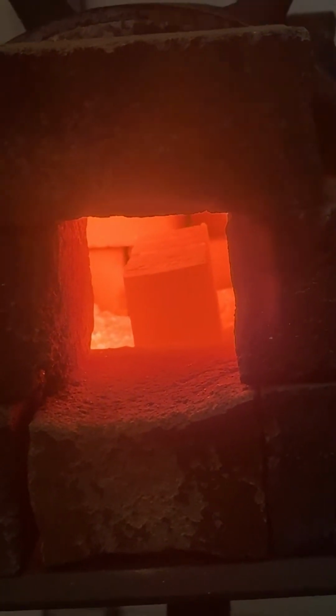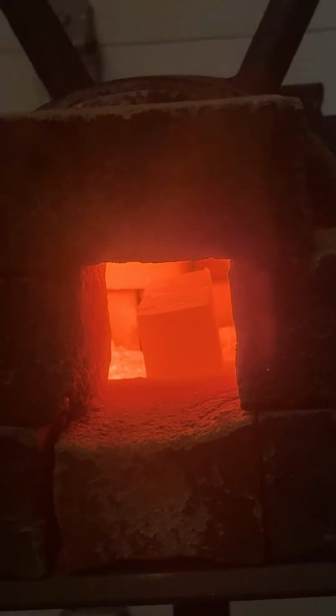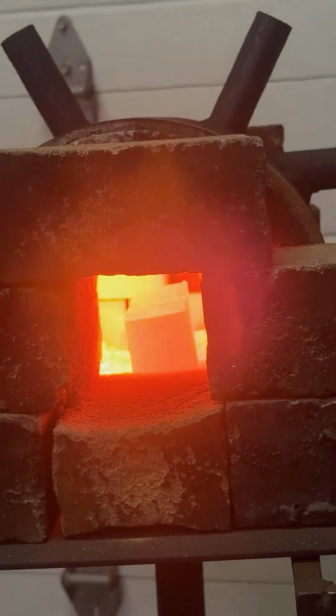Of course, light adjust, but yeah, that steel's sitting at probably about 2,000 right now. Pretty dang hot. I think what happened, why I didn't forge it down farther from that 3/4 to the 1/2 inch, is that it would have added a lot more time. And I wasn't interested in forging anymore after a couple of setbacks that I was able to recover from.